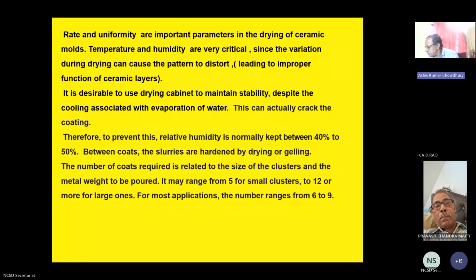Are very critical since variation during drying can cause the pattern to distort, leading to improper function of the ceramic layer. This drying is a very slow process. In order to maintain uniformity, the environment has to be always stable. It is desirable to use a drying cabinet to maintain stability despite the cooling associated with the evaporation of water. This can actually crack the coating. Therefore, to prevent this, relative humidity is normally kept between 40 to 50%.